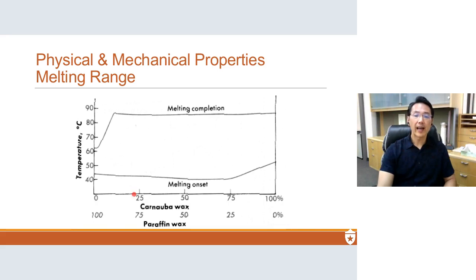So if we look at this, you have the composition of the wax. So you have no carnauba, 100% paraffin, 100% carnauba here. And as you add more carnauba into the mixture, you'll see that the melting begins when it's 100% paraffin at, I don't know, 43 degrees and ends at like 61. But as soon as you add a little carnauba, that melting range further widens. And with as little as maybe 12% carnauba, the melting range is from 40 all the way to like 89 degrees Celsius, okay?